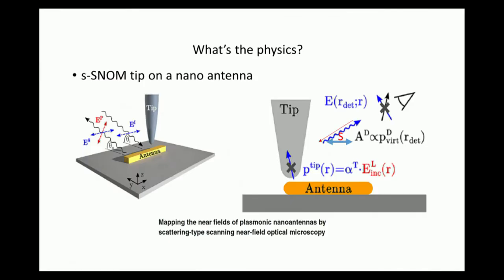So you could map a much smaller dimension compared to a normal lens-based approach, where you can only collect signal from about lambda by 2. We indicate about 200 nanometer ballpark minimum. Beyond that, there are not many sources which can go less than that. So we're talking about hundreds of nanometers versus tens of nanometers.